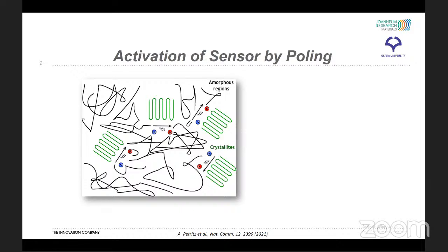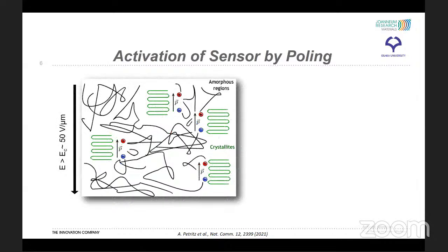After processing, the dipoles of the ferroelectric crystallites, here illustrated in green as green lamellas, are randomly oriented. Therefore, an electric poling field has to be applied in order to preferentially align the dipole moments and achieve a non-vanishing macroscopic polarization across the layer. Under opposing electric fields that are larger than the coercive field, which is about 50 volt per micrometer in the copolymer, the dipoles reverse their orientation repeatedly. And this is illustrated here as an axial rotation of the polymer chain.